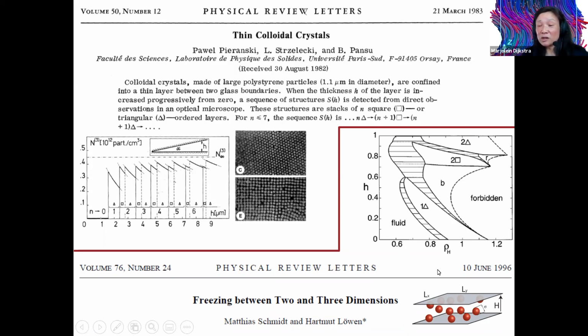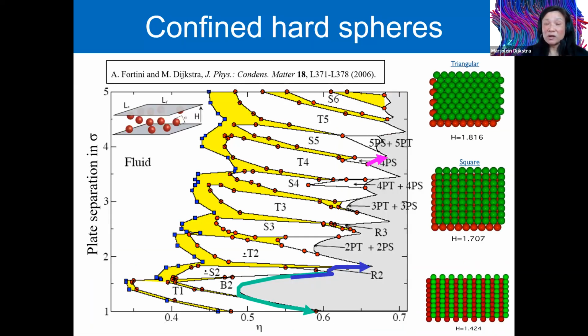Matthias Schmidt and Hartmut Löwen found that there were also intermediate structures like a buckling phase and a rhombic phase, and we revised this phase diagram by just using free energy calculation, and we found many more intermediate structures as well. So this buckling phase, the rhombic phase, but also a whole zoo of prism phases. So one can, for instance, take a path along these best packings. So they are these paths here. The gray region is just beyond the maximum packing, and just along these lines are the best packings for that system at that plate separation.